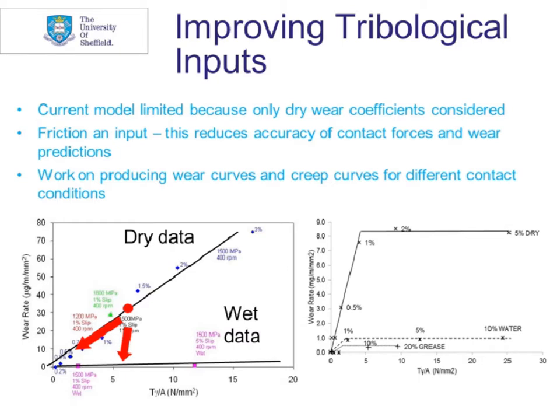However, if you think, for example, you're going to be going around a curve where there's some grease lubrication, then you could reduce the friction coefficient. Or if it was going to be wet, then you could reduce the friction coefficient. Well, within the modelling approach, as we've prescribed it, that would take you back down to a lower T-gamma value, but down this dry wear curve. And as you can see from the graph on the left, it would obviously give you a lower wear rate.